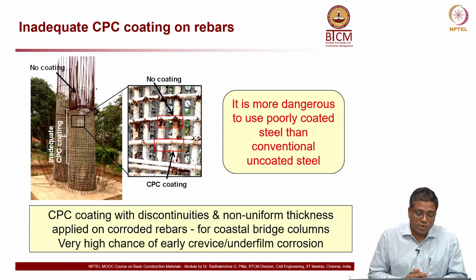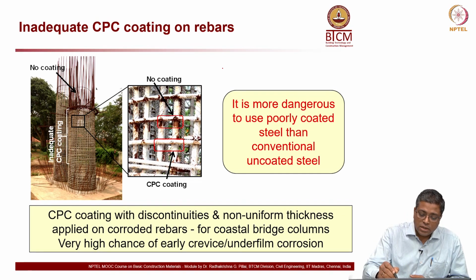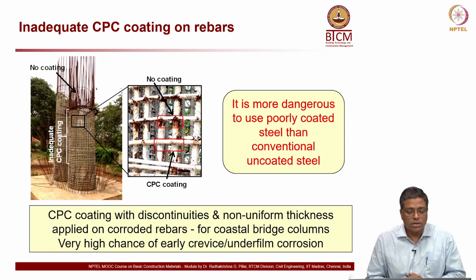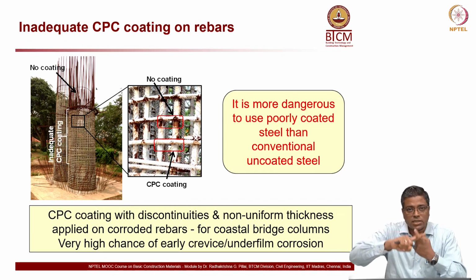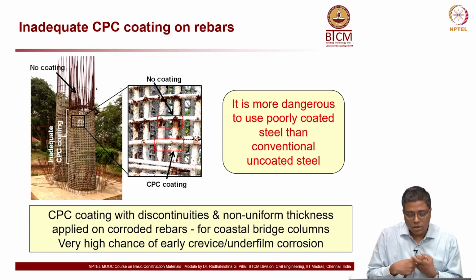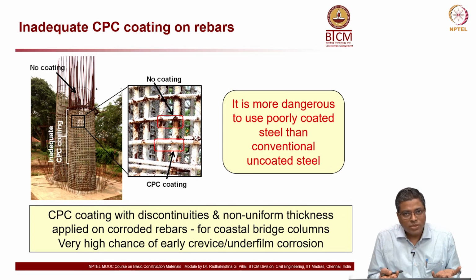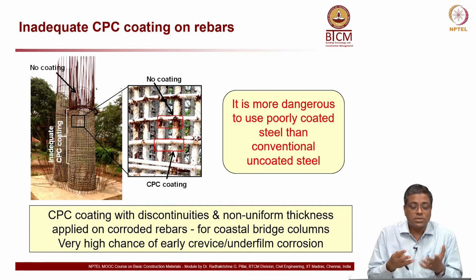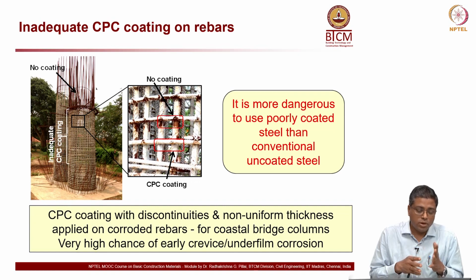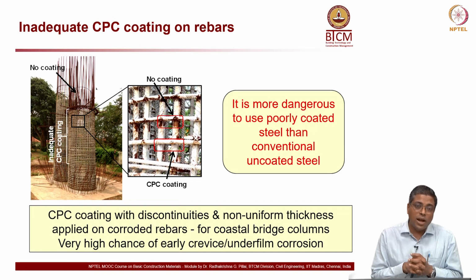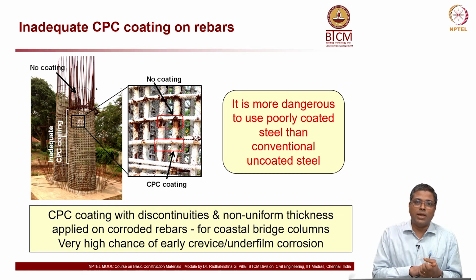And this is a picture from one of the bridge sites, where you can see this kind of coating applied, but there are a lot of places missed. I have put red rectangles in the zoomed-in photograph, where you can very clearly see that the joints, or the intersections between the vertical and horizontal bars, are not painted at all. When you have these discontinuities in the coating, there is again a possibility of a battery, or corrosion cell, being formed. So, you are actually creating a more vulnerable scenario by inadequately applying the coating.